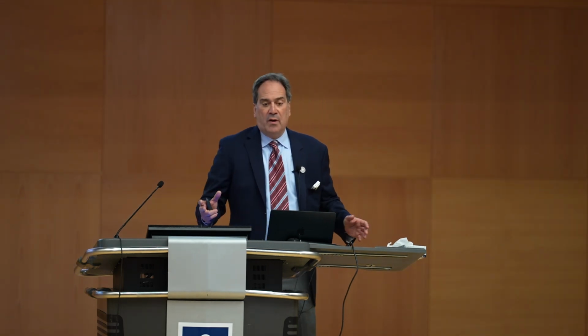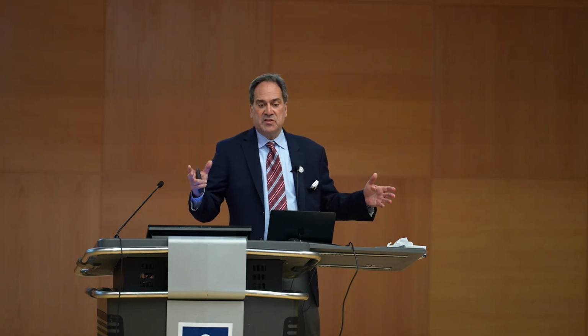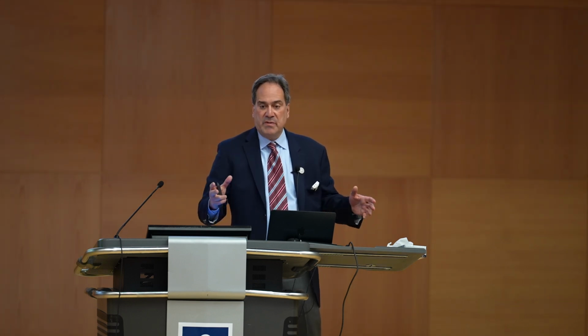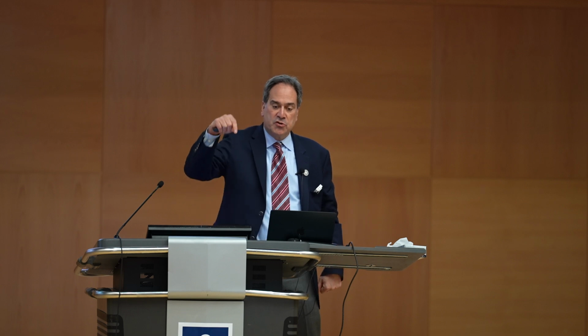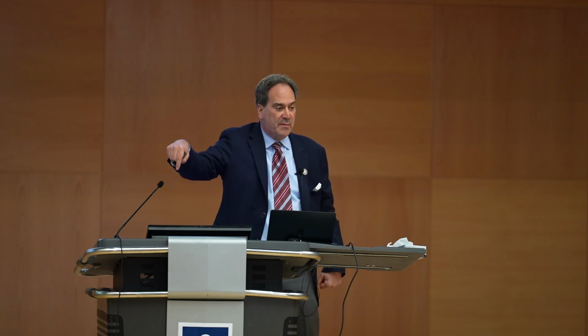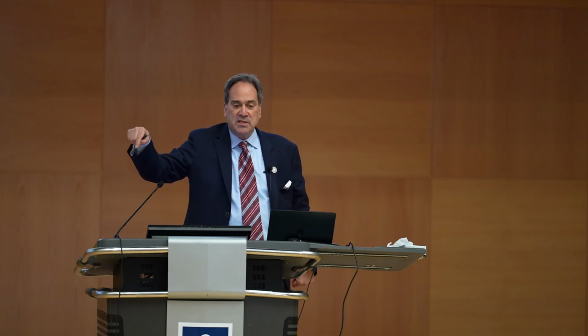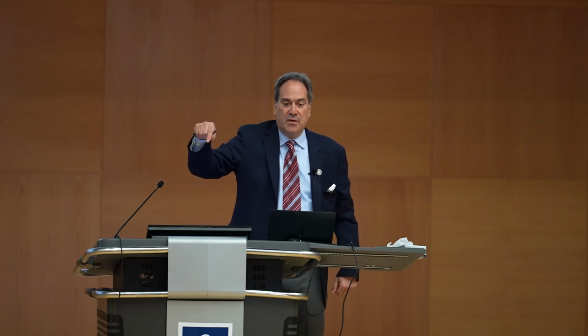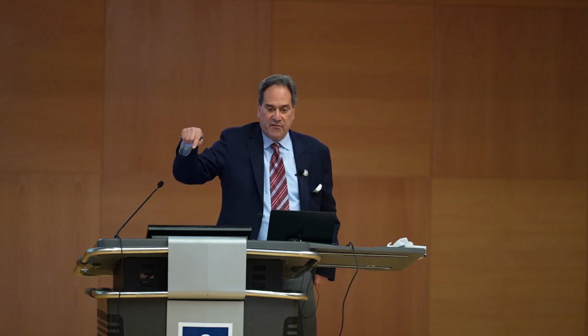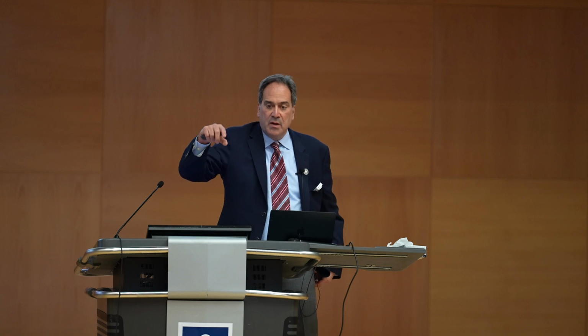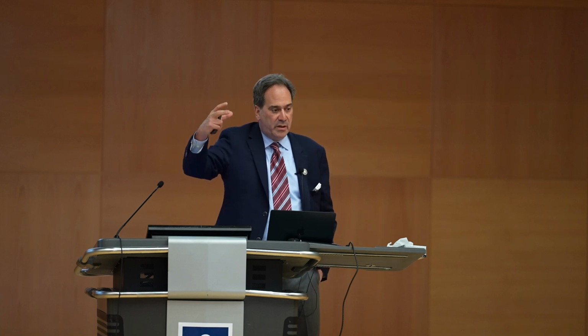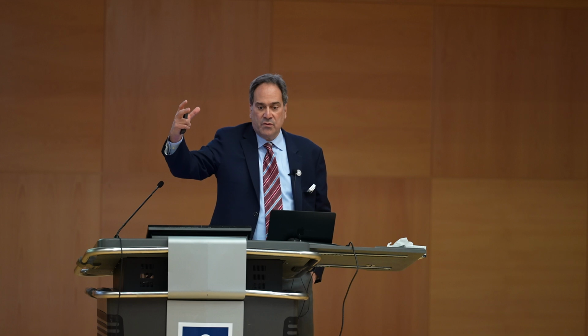What about going small? I used to tell the students, look, we should be able to go down to a single atom. Just keep diluting. Make these reactors smaller and smaller, and eventually you should be able to place a single atom here and a single atom here. That's conceptually possible. It's practically really difficult. And the reason is not because you can't find it, because we know where it has to be, but when you keep diluting the loading of the metal salt within the polymer, you run into a sampling problem.